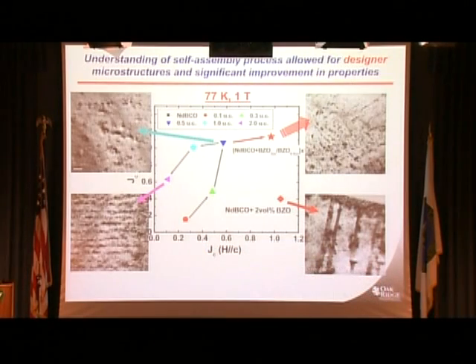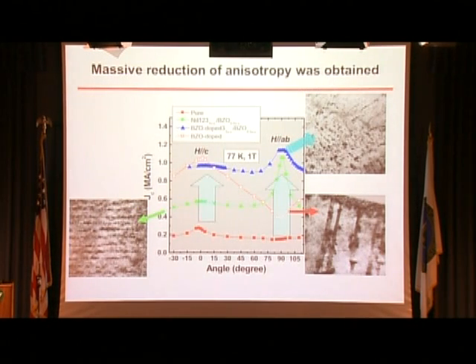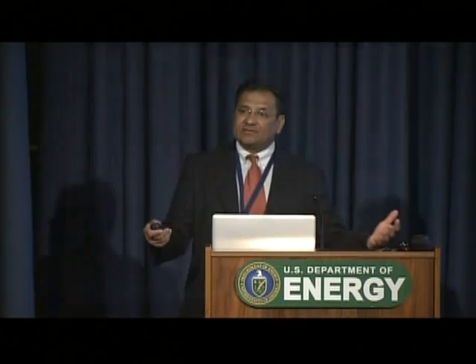By modifying the strain, we can align these nanocolumns in a perpendicular direction to the c-axis. And we can go to here where we've got these columns aligned in both directions. And then we get this massive enhancement that we were looking for. Now, if you were to look at the angular dependence of these 3 microstructures that I showed you, going from here to here, you can see that this red curve is the amount of current you can pass as a function of magnetic field orientation to the c-axis. You can see this red curve is without these nanostructures, and the blue curve is with these nanostructures. And you can see that you can get this massive enhancement.